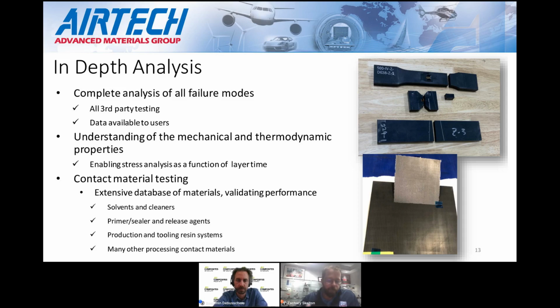So with 3D printing, there's kind of this Goldilocks zone where things are not too hot, where they can still remain stable. But then you also want to deposit material back in a timely fashion so that you get good mechanical properties. So really the drive here is to enable stress analysis as a function of layer time. So we can take the slice geometry, look at what the deposition time is going to be, and perform a stress analysis prior to printing.